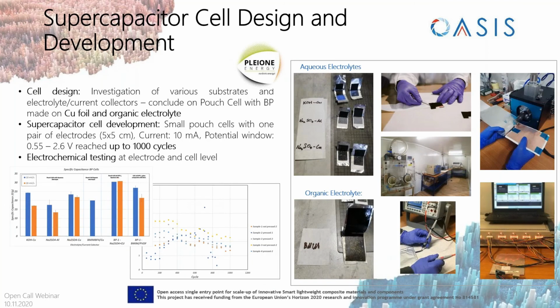Pleione, together with Tecnalia, has also investigated various substrates for the transformation of Bucky papers into self-standing electrodes, starting from conventional copper foils, aluminum foils, and other metallic foils. Also, different electrolytes and current collectors have been investigated for the manufacturing of the supercapacitor cells. And based on the results, we have concluded on pouch cells with Bucky papers made on copper foil and organic electrolyte.